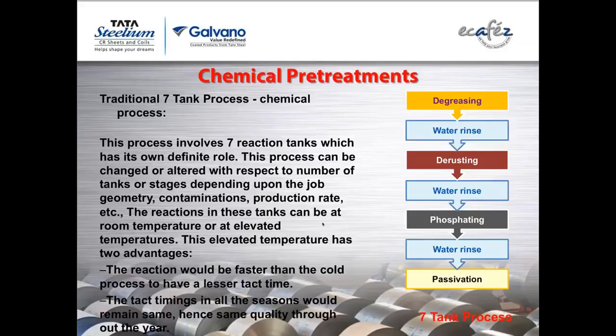So one dip there, then you go for phosphating, and phosphating again you have 2 or 3 different types. One is iron phosphating, second is zinc phosphating, and third is manganese phosphate. Manganese is not used for coatings, but zinc and iron are used. Now iron will not give you as much corrosion resistance as zinc phosphate. So normally zinc phosphate is preferred for corrosion resistance. Ultimately, after a water rinse, the final tank is called passivation. Now if you are exporting, chromic acid passivation is not to be used because chrome is banned. So you will get chrome-free passivations also.